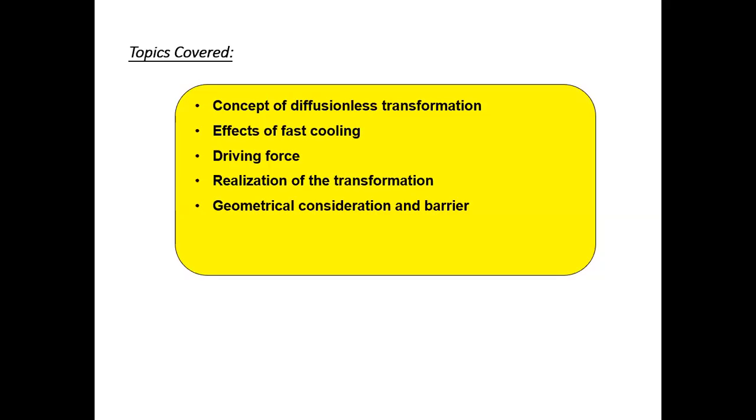It's more like a geometrical pathway, where we deform the box from the cuboid to the cubic, while also considering the constraint of packing. We showed that this is doable but necessary to introduce a huge elastic energy, possibly a barrier, and the material has a very smart way to compensate for this energy by developing twinning structures and boundaries.